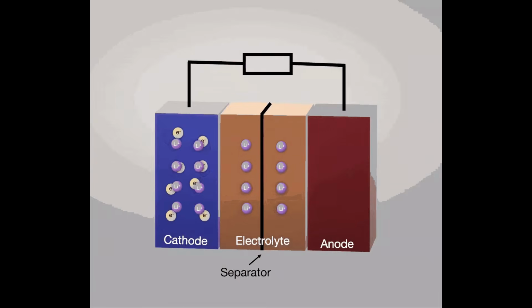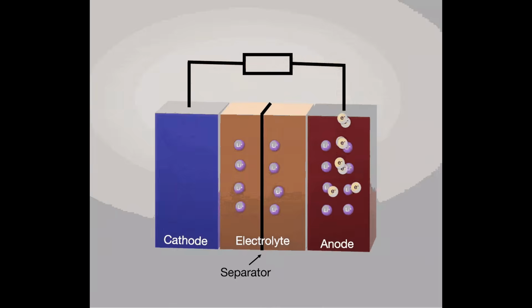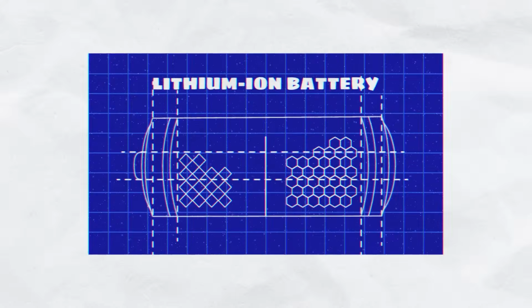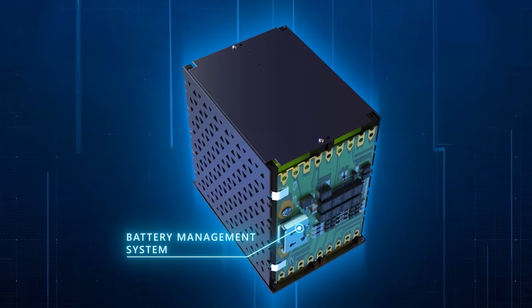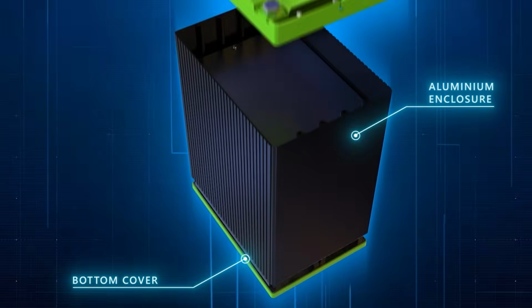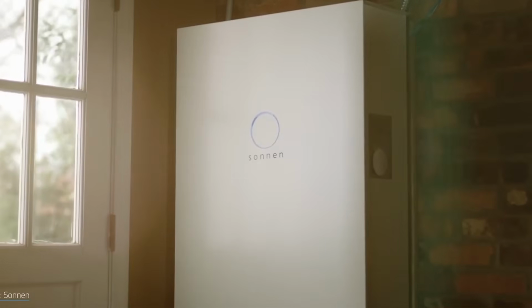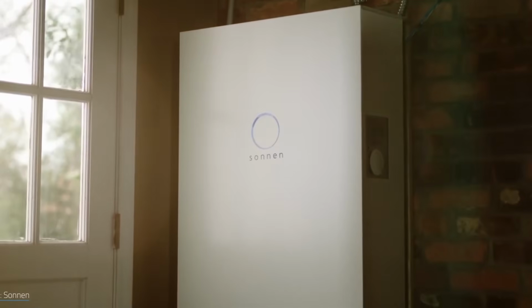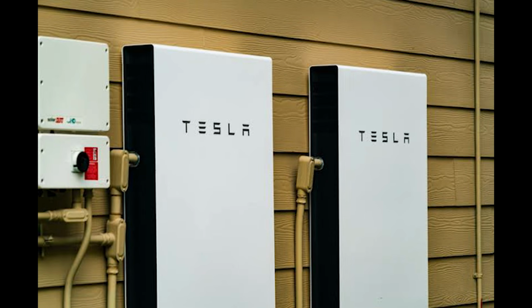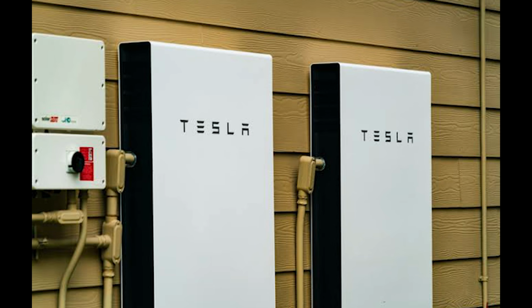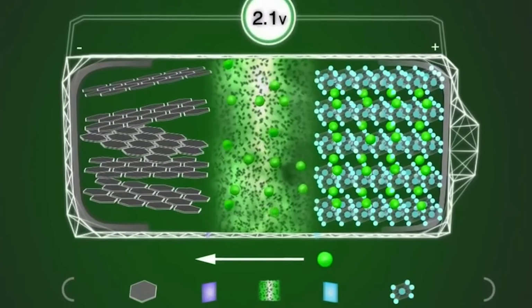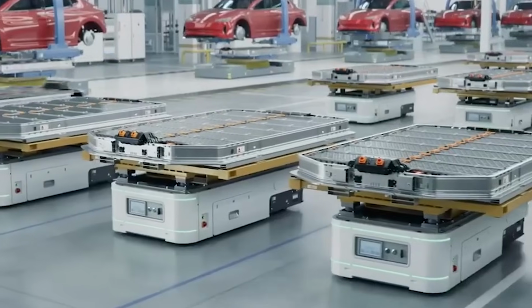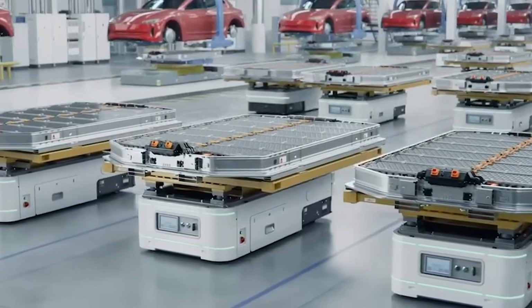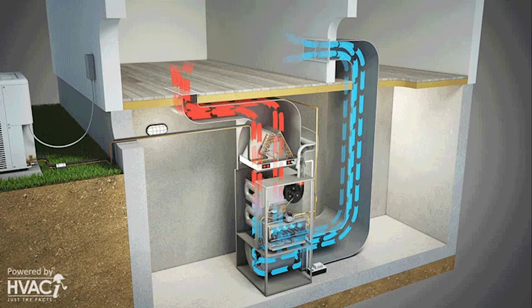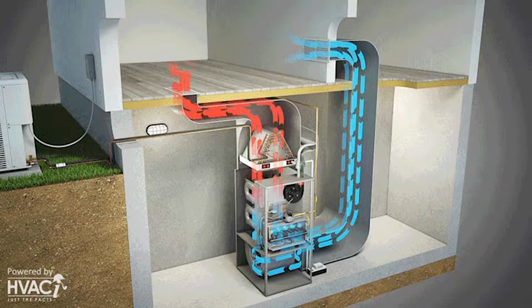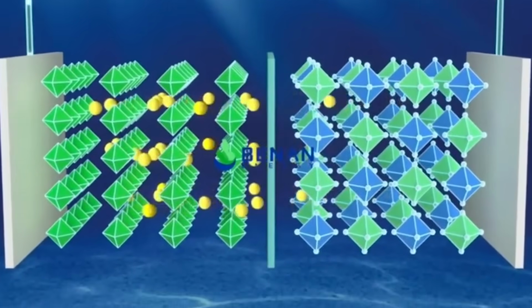Lithium iron phosphate cells start losing discharge capacity below 32 degrees Fahrenheit. By the time you hit -4, most packs are throttled to half their rated output or less. At -20, many shut off entirely to protect themselves from irreversible internal damage. The Tesla Powerwall 2, for example, lists an operating range of -4 to 122 degrees Fahrenheit, and its discharge rate drops significantly toward that lower boundary. A battery that quits when the furnace needs it most is not backup power. It's an expensive box in your garage with a warranty card.